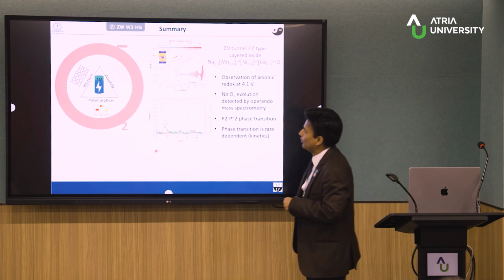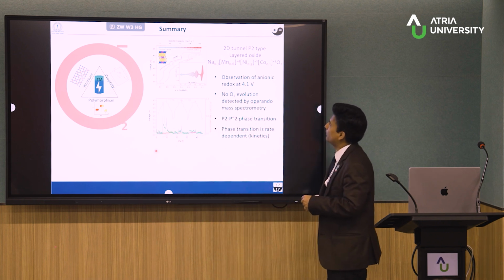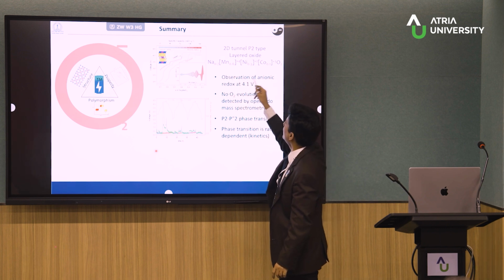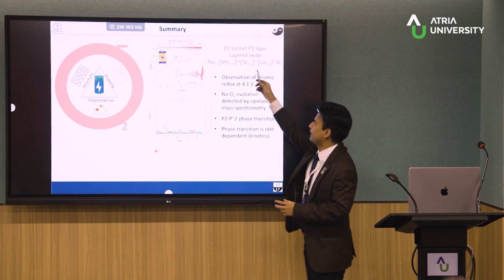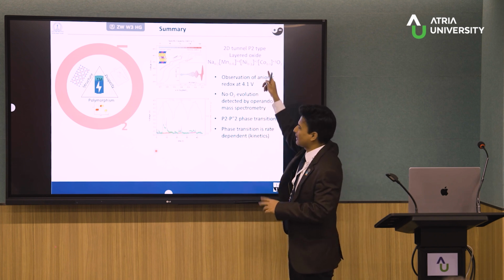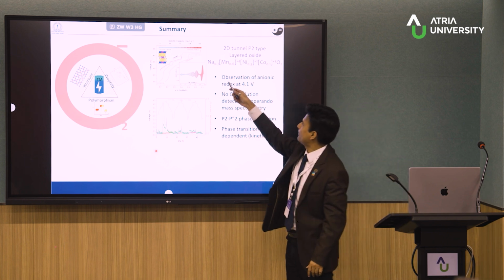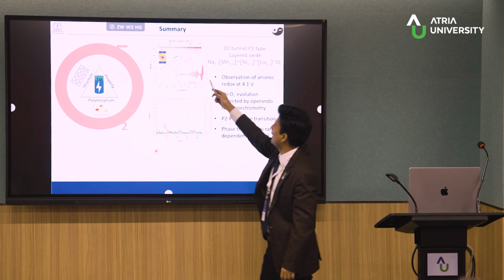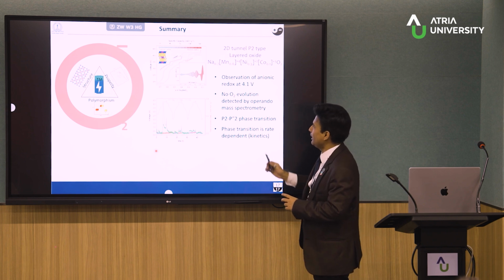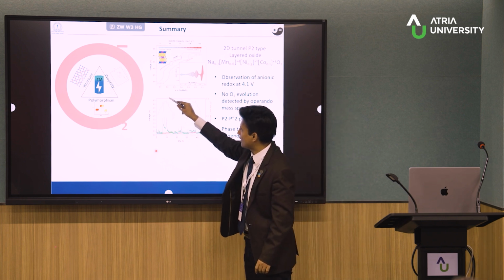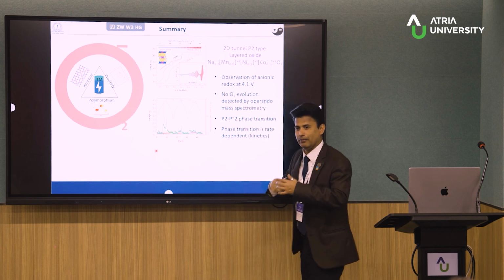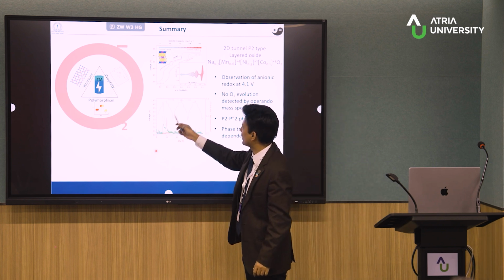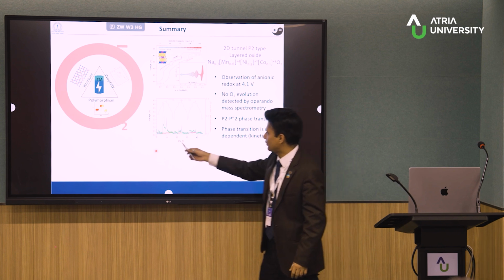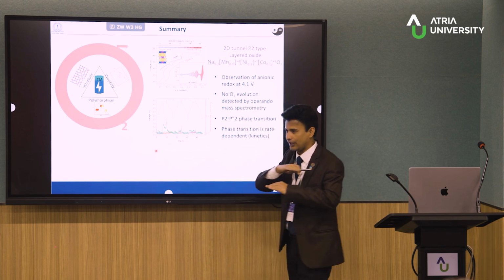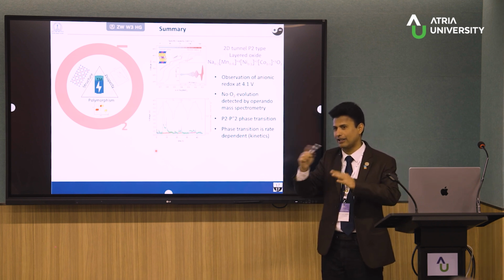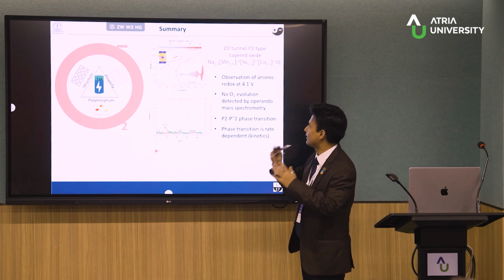So to summarize my talk, we are talking about the anionic redox, oxygen redox. For that we came up with this new composition derived from Na0.7MnO2 by substitution of nickel and cobalt. Nickel basically gives a high cationic potential, and 10% cobalt gives some structural stability, cycling stability. In this material we found 4.1 volt anionic redox at very high voltage, which is reversible. And when we do the DEMS analysis, we found that during the charge discharge there is no oxygen evolution. This is very important. In many anionic redox materials, some oxygen evolves. Initially in the first two cycles we get some CO2 and CO because of electrolyte decomposition, but if you see the red curve here, throughout the first three cycles there is no oxygen. So the anionic redox is happening, but oxygen is not coming out. It is inside the system and it is reversible, which is a good thing.